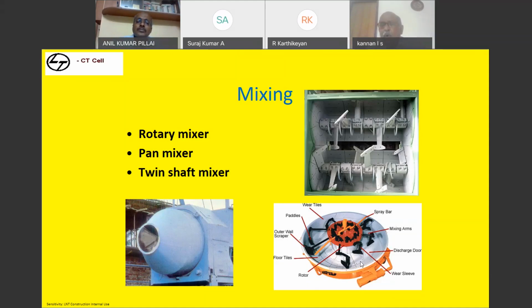If the gap is more, automatically you will find a lot of accumulation of material at the bottom. Generally, when we receive concrete at site from the transit mixer, when we start delivering the concrete, we find a lot of aggregates rolling out. It is because the gap in the batching plant is more, so only dry material is getting fed to the truck, and unmixed aggregates roll out in the initial phase. That means the batching plant needs attention.